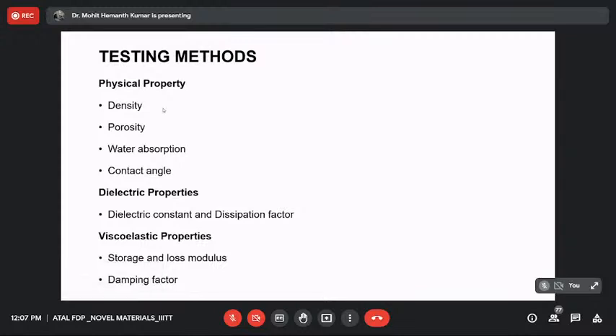with the help of our TGA curve, that is how we select this. First, we have to go for TGA. From the TGA, we have to check what the degradation temperature is. According to that degradation temperature only, we select the operating temperature range for this viscoelastic testing. From this, you will get the storage modulus, loss modulus, and damping factor. From the damping factor, you will get the glass transition temperature, which cannot be equal to the DSC glass transition temperature.